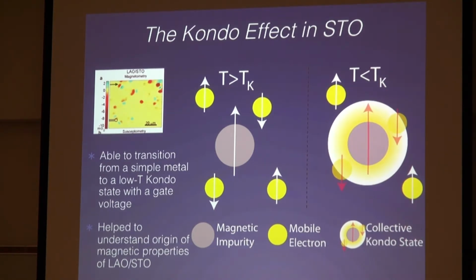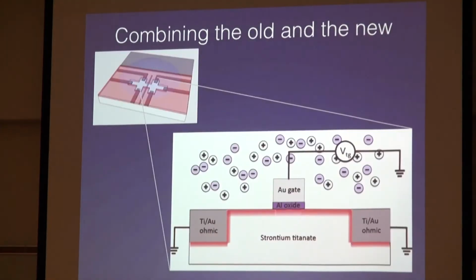And one of the first things that we did with this system was we were able to start with an insulator, turn it into a metal, and as we continued to turn up the voltage, we were able to induce a Kondo state where there seemed to be localized magnetic impurities that were being screened by the itinerant electrons. I think this is the first time in 2 dimensions that you've been able to tune from an insulator to a metal to a Kondo state. And this work was really able to start to explain some of the emergent magnetic properties that people have seen in both STO and at this interfacial system, LAO-STO, which is basically a way to get a 2-dimensional electron gas in STO.